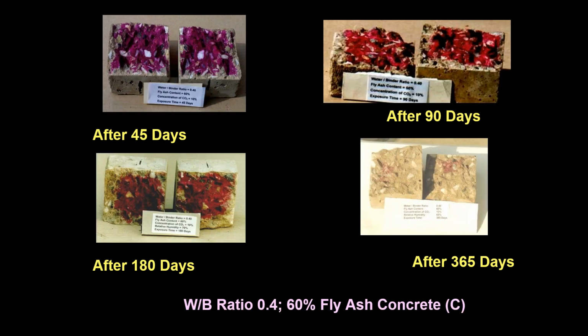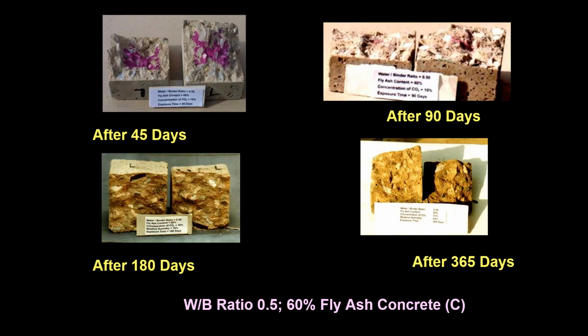Yeah, you can see this is quite an interesting case. Water binder ratio 0.4, 60% fly ash. At 1 year, fully carbonated. At 180 days, you can see the progress of the carbonation. Of course, this is under accelerated condition. Now it's quite an interesting case. Water binder ratio 0.5, 60% fly ash. You can see the carbonation started at 45 days itself. At 1 year, totally carbonated.